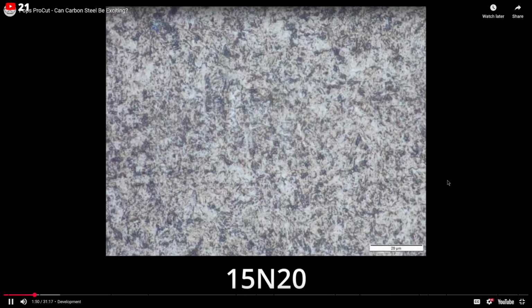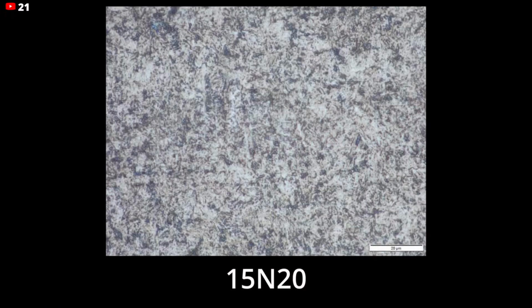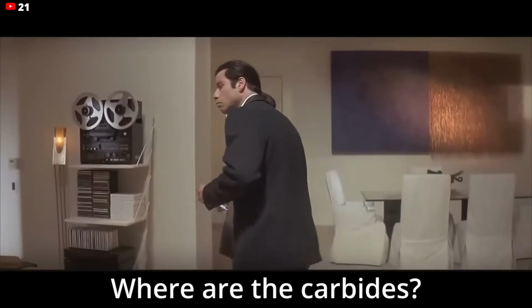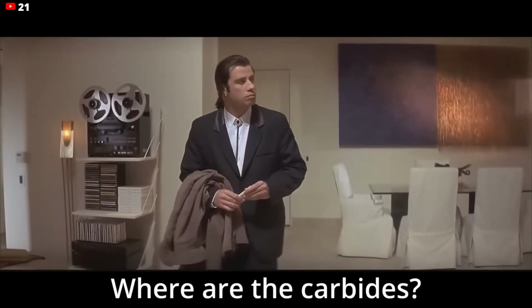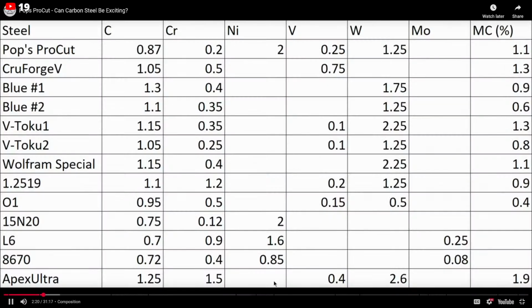So one of the things that I thought about was that our selection of high nickel steels is very limited. So 15N20, L6, and 8670 are pretty much it. And those steels are really high in toughness, higher than 80CrV2, and they offer good hardness to go with it, but they don't have any wear resistance at all. There's almost no carbide in there. So I thought if we added some tungsten and vanadium to a high nickel steel, we could make the steel more balanced, give it some wear resistance along with that high toughness. This could give us better toughness and better wear resistance than an 80CrV2.